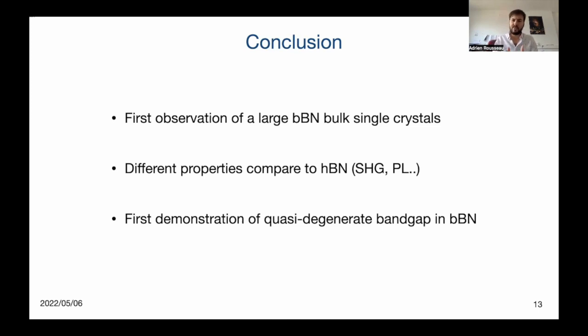Finally, we first demonstrate the existence of a quasi-degenerate band gap in Bernal boron nitride, where indirect transition and direct transition are in competition.